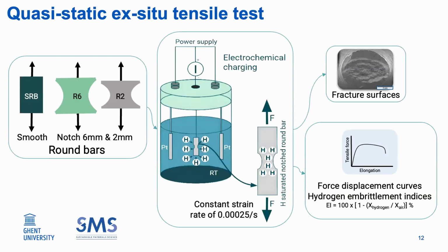The round bars here are also extracted from the pipeline middle region, having different notch geometries, simulating different stress conditions. Then, based on the conditions that we acquired from the hot extraction exercises, we applied the same conditions and charged our samples electrochemically until saturation, and then subjected these round bars to a tensile test at a constant strain rate.